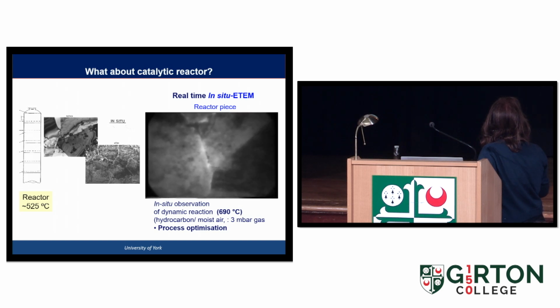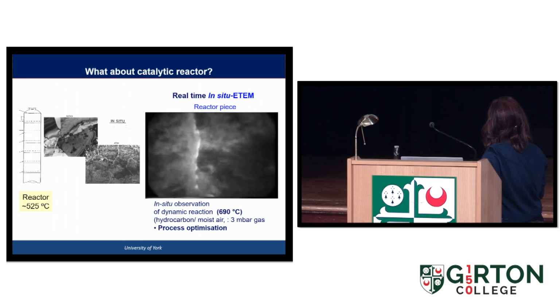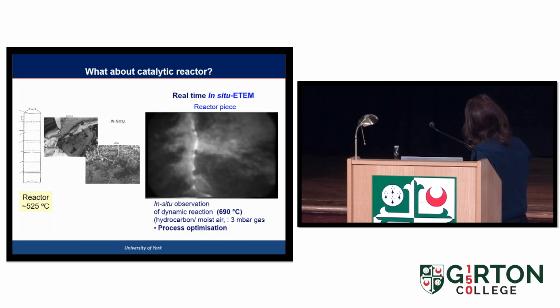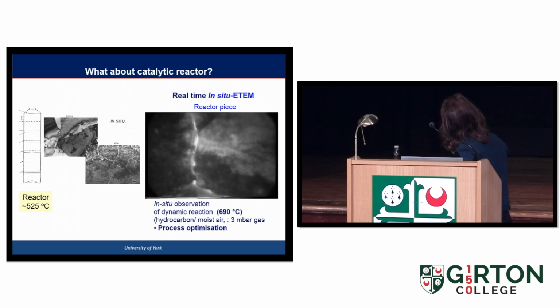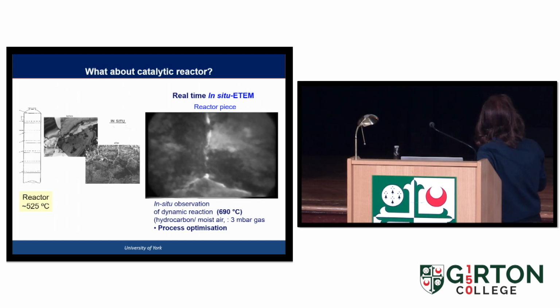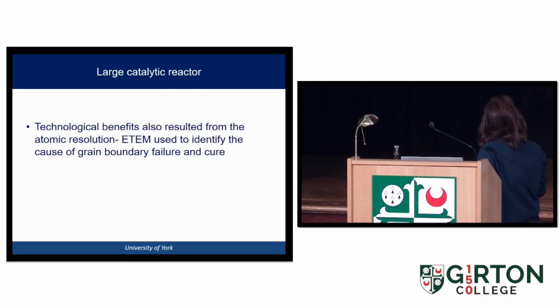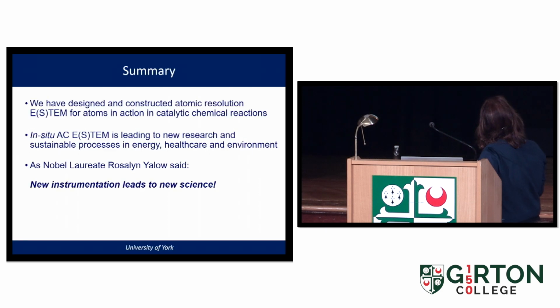Exactly what they observed. But this was actually happening at 690 degrees C, and the reactor was supposed to be at 525. So immediately we saw that there were hot spots in the reactor. We told them, and they were able to save the reactor. So technological benefits have also resulted from the atomic resolution ETEM used to identify the cause of grain boundary failure and cure.